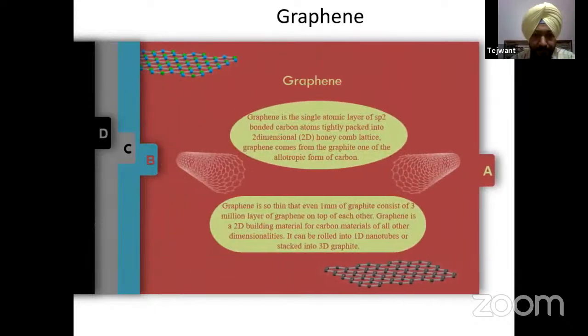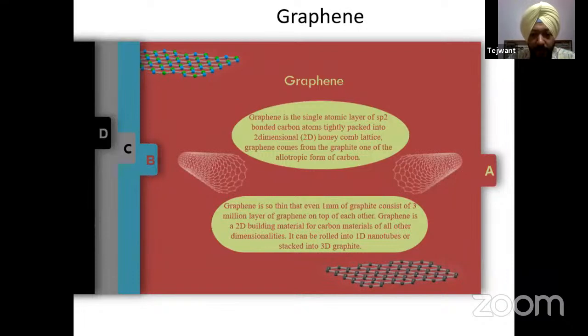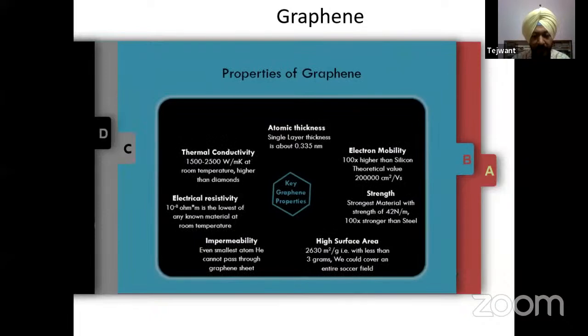What is graphene? Basically, graphene is a single atomic layer of sp2 bonded carbon atoms tightly packed in a two-dimensional honeycomb lattice. Here I have shown you certain structures. These are just the sp2 bonded carbon atoms, six carbon atoms packed in the form of a honeycomb-like structure. If we fold the graphene, it forms carbon nanotubes. Basically, graphene is exfoliated from graphite, and it exhibits many unique physicochemical properties. Its atomic thickness is very low: a single layer of graphene has a thickness of about 3.35 angstroms. The electron mobility is very high, about 100 times higher than that in silicon by theoretical approximations.